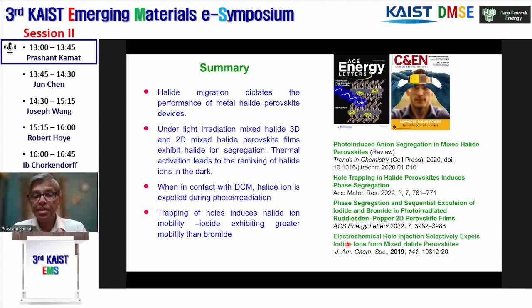Under light irradiation, these 2D and 3D both undergo phase segregation. In the dark, they would like to be in the mid state. The 50-50 case we studied was an extreme case, just to see how these ions move. In a practical device, these are greatly suppressed when you use triple cation or other compositions. The case I am presenting here is just to demonstrate how we can monitor these changes under extreme conditions.